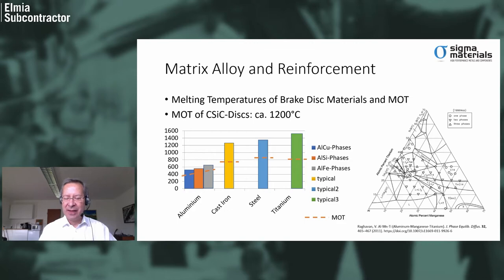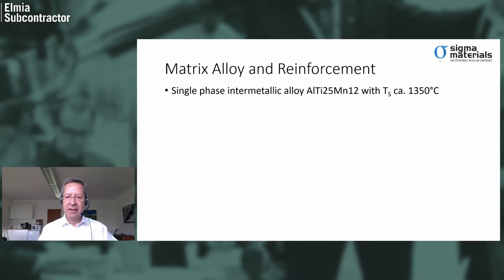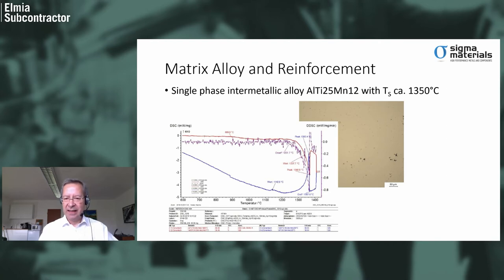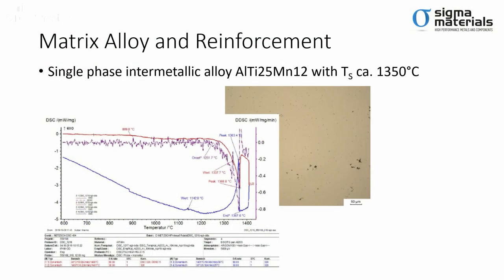Luckily, we found a system that consists of aluminium, titanium, and manganese, which has an area where it consolidates in a single phase in a cubic form, which means that it has at least a little bit of a ductile phase. And the attractive properties are low density at about 3.7 grams per cubic centimeter, and a melting temperature of about 1350 degrees. There are also other nice effects. We see in the melting and heating diagram that we don't have a phase change until above 1100 degrees. That means that we don't have any issues with phase changes and hot cracks with this material.